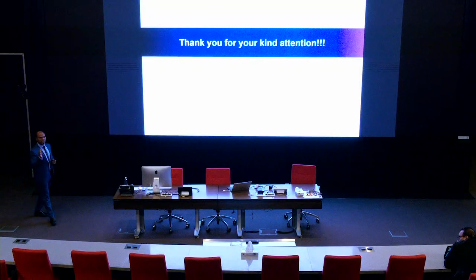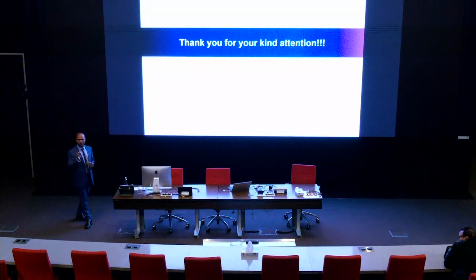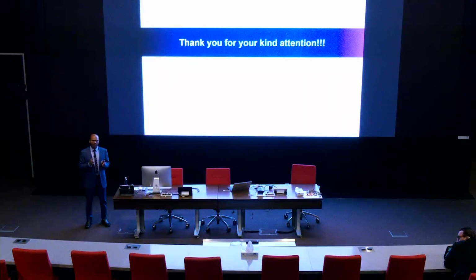No, that's what it is. The commercial calculation they have done is that to make it more commercially viable, you have to have a solar to hydrogen conversion efficiency of 5 to 10 percent. So now we reached 4, right? But if you reach 5, or even with the 4 with the government subsidy, yes, it is possible. But once you reach that 5, then we can have the target of $2 per kg. So that's the target that we are going to achieve.